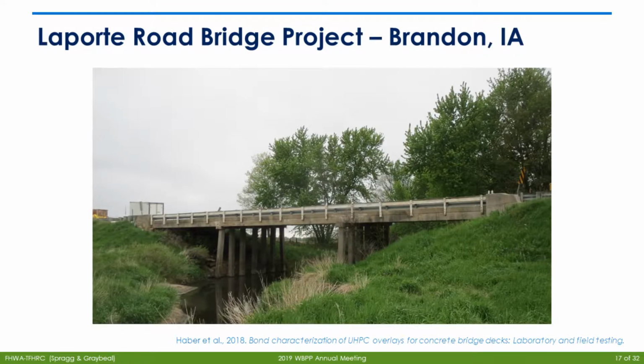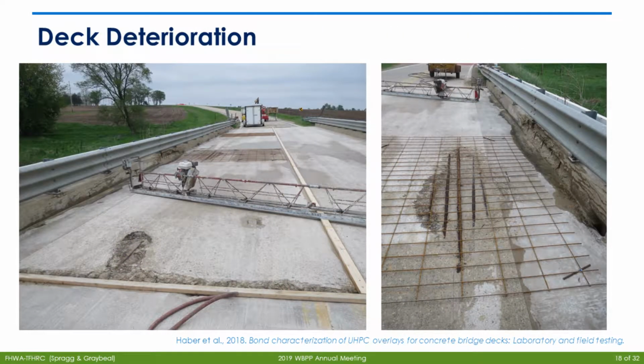Transitioning to projects that have happened here in the United States, this is one that happened in Brandon, Iowa. So you can see it's a relatively low volume road, of course. But here's a picture of what the deterioration on the deck looked like. So you can see some spots with a significant amount of spalling. Again, they did put some reinforcement. That's depending on the design of the overlay, whether you would need reinforcement or not. And then, of course, in the large potholes that they cleaned out, they also put some rebar in there as well. And then they hydromilled prior to putting the overlay.